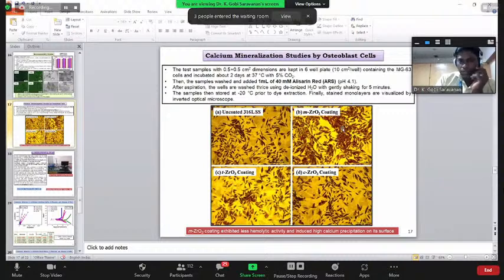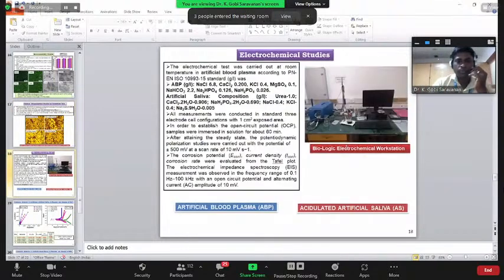This red dye shows the calcium phosphate, the calcium crystals. This is called alizarin red dye, and it will bind with the calcium wherever it is there. So from this figure, the red color shows that monoclinic zirconia has higher proliferation of osteoblast cells than the cubic as well as tetragonal. So it indicates that monoclinic zirconia is capable of a high number of proliferation in osteoblast cells too.